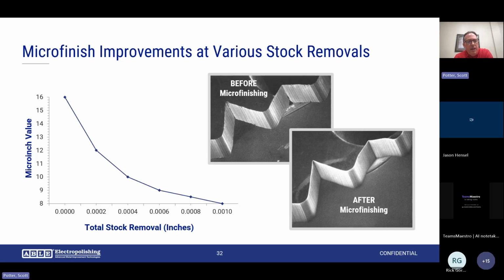Here's a chart that gives you an idea of the micro-inch improvement as it relates to stock removal. You can see on the left of the graph, you're starting out at a 16 Ra, and as you take more stock removal, you get that gain in the Ra surface finish. You see where it took it down to an 8. Typically, the rule of thumb is that with 0.0005 inch stock removal per surface, or per side, you're going to get 50% improvement. So that's a key benefit.